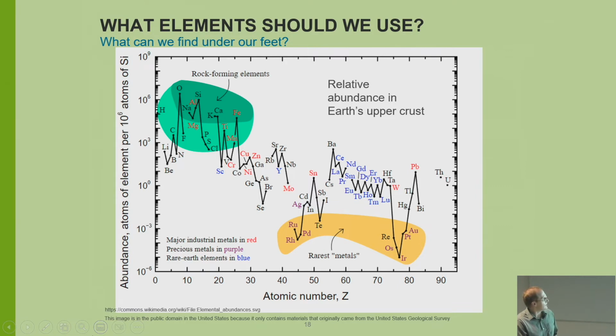Cobalt, it's about 15. Nickel and copper are just a little bit higher, a little bit more abundant, but cobalt is difficult. And also, where does the cobalt occur? So common things like your iron, manganese, there's no issue about really running out of those, and for that matter, aluminum. Your lithium isn't too bad. These are actually the rare earth elements, which really aren't all that rare. They're just called rare because at the time they were rare. But something like lanthanum, the lanthanum nickel 5 in the nickel metal hydride battery, that's as abundant as cobalt. If you look at your rare earth metals down here, this is what's in your catalytic converters. This is why people steal catalytic converters. So you're looking at, what was it, 1 atom of platinum or palladium for every billion atoms of silicon. And if you think of iridium, that's your kryptonite for dinosaurs. So that's even more rare.